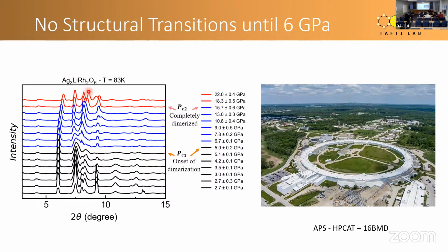We also performed these experiments at lower temperatures, and again, the same thing. We saw that this structural transition doesn't happen until 6 GPa.